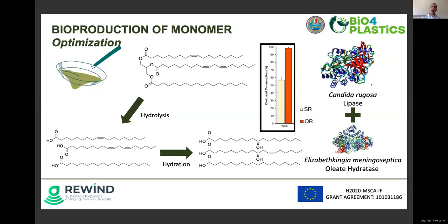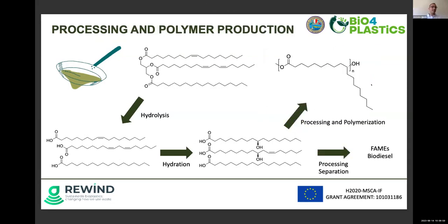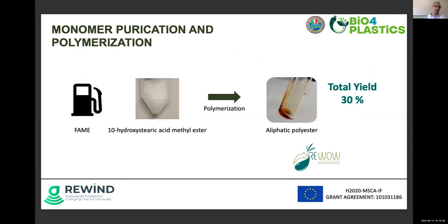And we could see that with the optimized reaction conditions that we obtained through a design of experiments, we were able to increase oleic acid consumption by up to 40%. Of course, we want these monomers to create the polymers. So we carried out the processing and purification of the monomer, and we were able to produce FAME, so these fatty acid methyl esters for biodiesel, and the monomer itself, which is the 10-hydroxystearic acid methyl ester. And then we were able to polymerize all of these with a total yield from the waste cooking oil to the aliphatic polyester of approximately 30%.